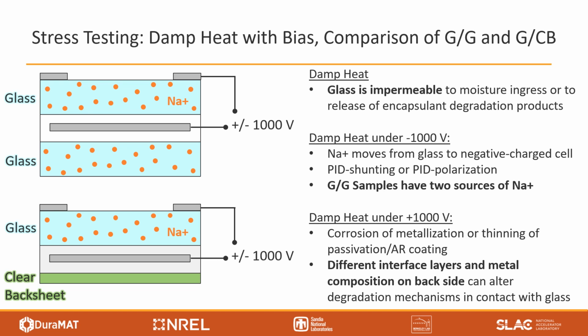The first obvious one is the impermeability of glass both to moisture ingress and to the out diffusion of encapsulant degradation products. The second factor is that glass supplies an extra source of sodium ions on the backside of the module. This could result in potential induced degradation by sodium migration to the backside of the cell under negative system bias, which wouldn't necessarily happen with a backsheet.